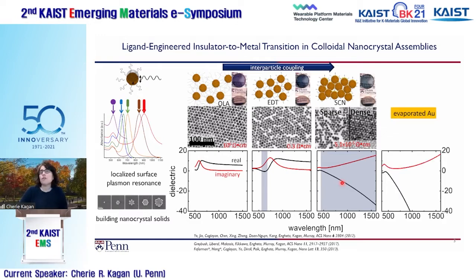And if we compare this to a film of evaporated gold, in the case of gold, you see that they start to fuse together, but they don't really form a dense structure. And so what happens is that we can dial in the dielectric function, and I'll say a little bit more about this shortly. In this example of the nanoparticles, the dielectric function is less negative than it would be from an evaporated gold film. And so the community working on optical metamaterials would really like to have the flexibility to design the dielectric function of materials more at will.